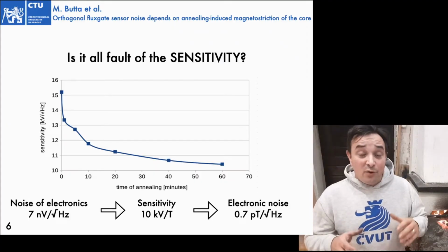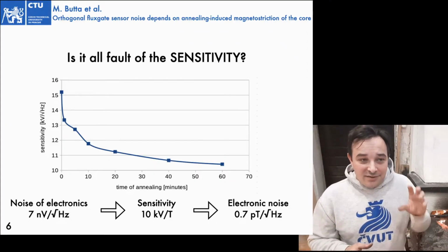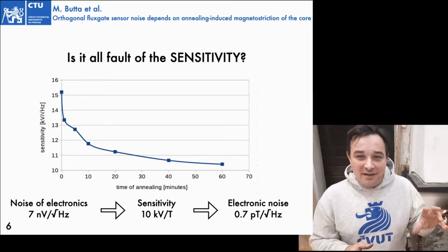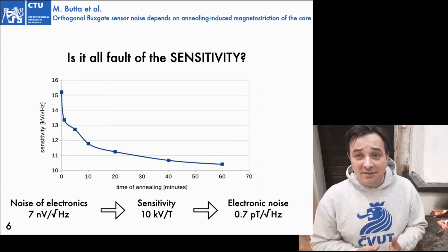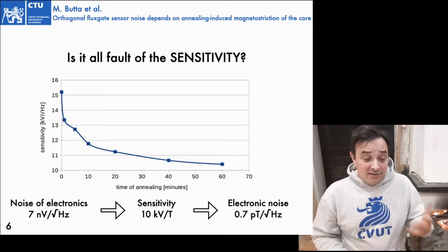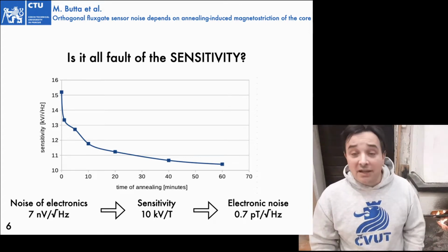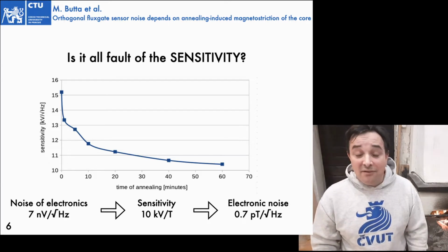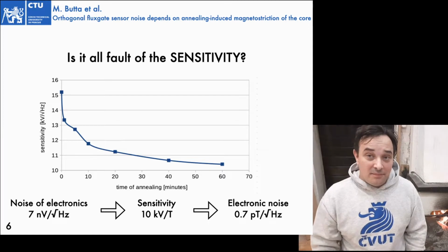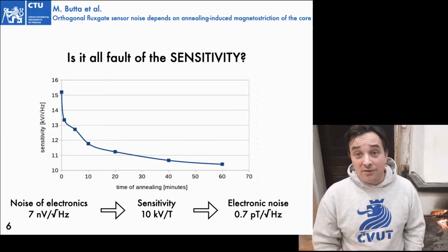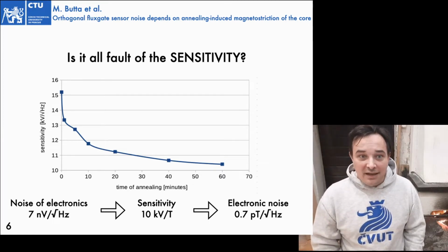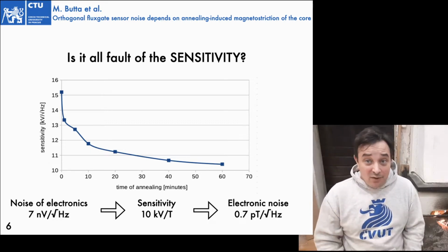But later on, we developed a special electronic, and thanks to a particular preamplifier at the pickup coil, we managed to achieve quite a respectable sensitivity, even for long-time annealing. For instance, you can see here that after 1 hour annealing, we still get 10 kilovolts per Tesla of sensitivity before amplification. And this means that the white noise of the electronics of the magnetometer accounts for 0.7 picotesla per root Hz at 1 Hz, which is very low, much lower than the noise that we observe.